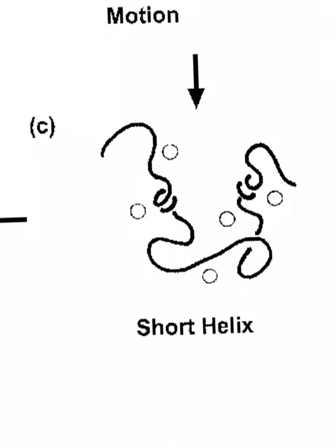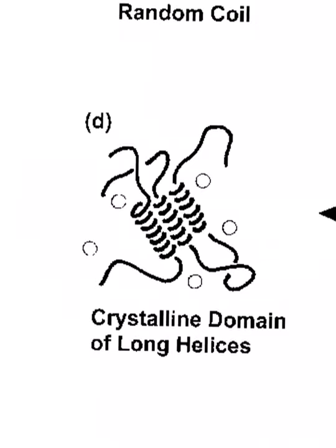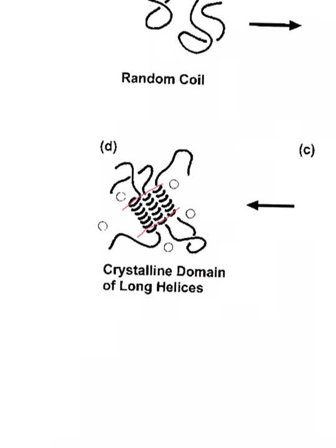And so what happens, again, in the real world, things aren't exactly the way we predict them, but you start forming helices in these structures. And that's where the crystallization really starts, where the puzzle pieces start fitting together, inside these rounded structures that have the same spacing between the polymer chains. Okay. And so this goes on, and eventually you end up with something similar to what we talked about before. You have a crystalline component, and outside that it's amorphous. Okay, and this is, as I said before, much easier in solution than it is in a melt, because there's lots of freedom out here for these polymer chains when they're not obstructed by other polymer chains present at high densities. Any questions about that?